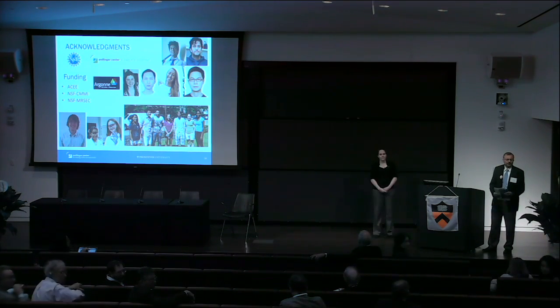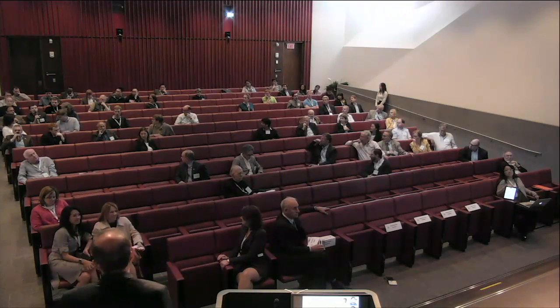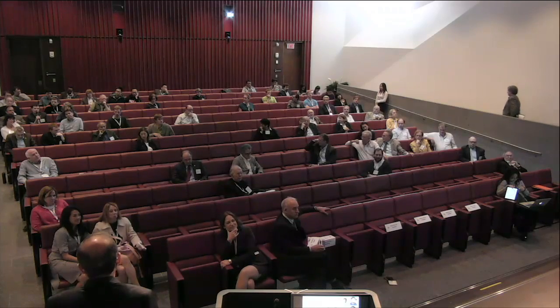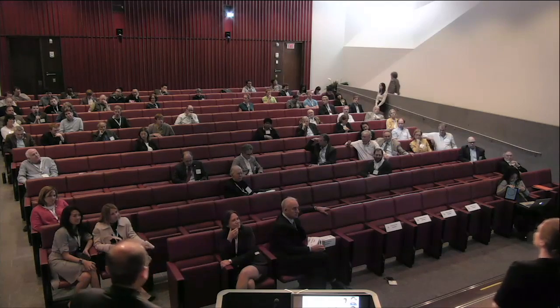Barry Rand from Electrical Engineering in the Andlinger Center. My question is about the bending test you guys do to get at the permeability. Presumably that's an accelerated sort of lifetime test. Is there a way to correlate the permeability value with how long it will live in real world application? So the permeability test is just to have an idea of how quickly water moves through the structure, and this tells us about mass transport of ions. So it's not actually an accelerated test. It's a test to get at the intrinsic permeability values without using force, like applied pressures.